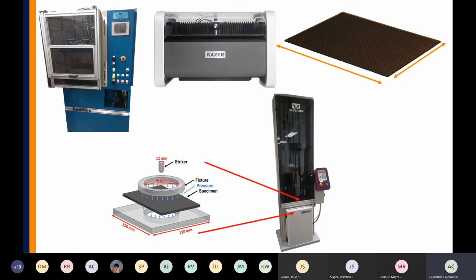CEAST 9340 drop weight impact machine, which consists of a striker that hits exactly the center of your composite. And then the door, that white door that you see over here, is an environmental chamber. So in my research group, we don't only look at what happens at room temperature, because your composite will not always be exposed to just room temperature. You have different environmental conditions such as low temperature, like for example, if you have a ship that is going through the Arctic, your ship might experience temperatures down to minus 60 Celsius, which are the temperatures in the Arctic. But also they can experience really high temperature.